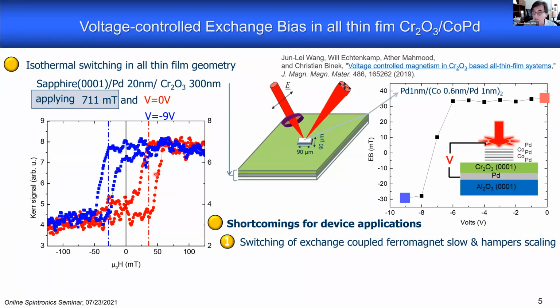In the other direction, it hampers it. So if you make your system thinner and thinner, these effects that come from the interface become more and more pronounced. And that's bad, because it means the system is not fully scalable to ever smaller sizes.